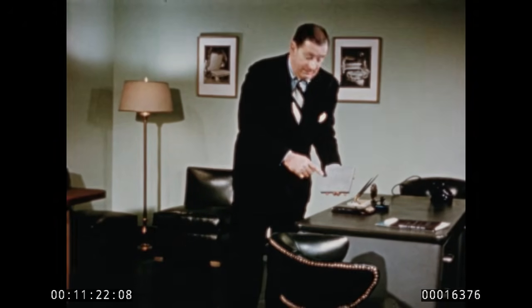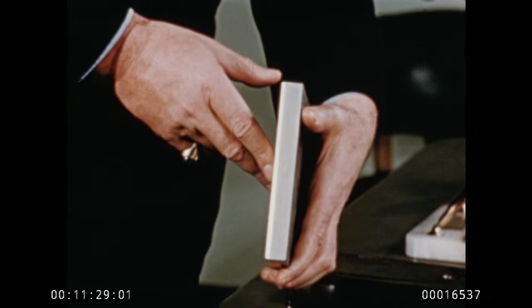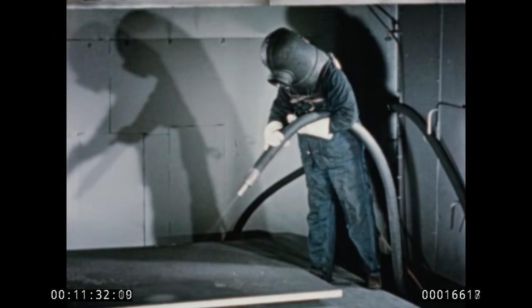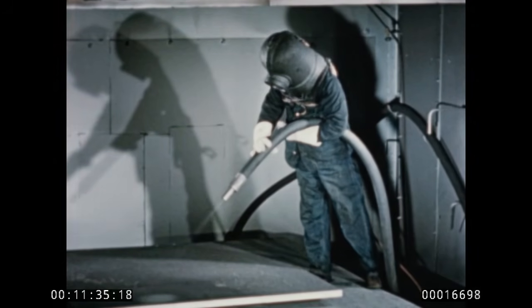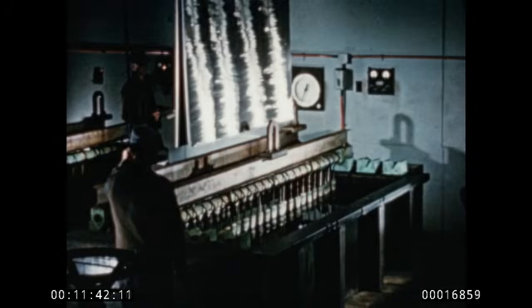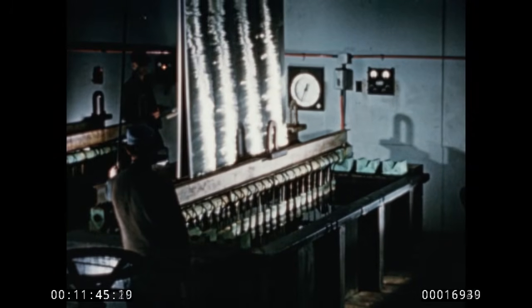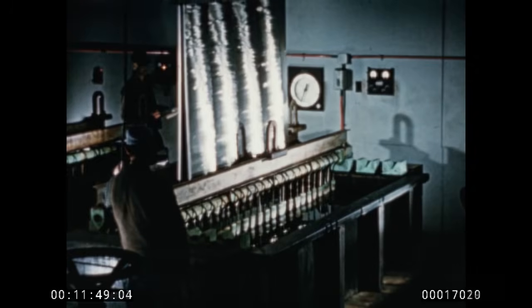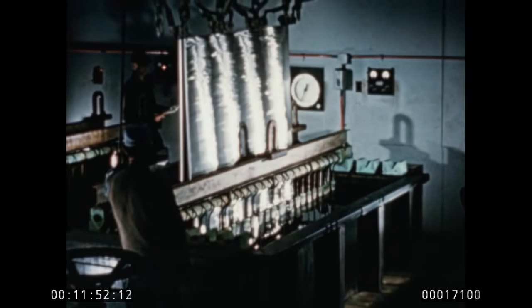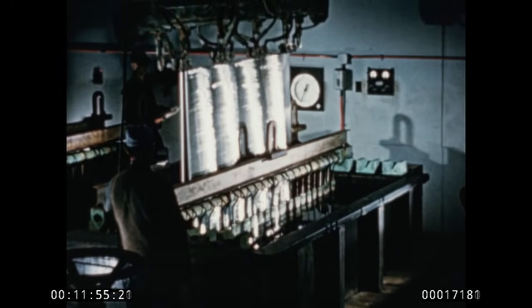The first thing we do to make a clad steel plate is get the alloy plate, called an insert, and the carbon steel backing plate absolutely clean. We take the time to do it thoroughly, because scrupulous cleaning is one of what you might call the secrets of making clad steel. Next comes nickel plating, done on most alloy slabs except nickel, of course. This is an important step that helps get the solid bond between cladding and backing plate that makes clad equipment so good. Nickel plating also acts as a buffer to limit possible carbon migration from the backing plate.